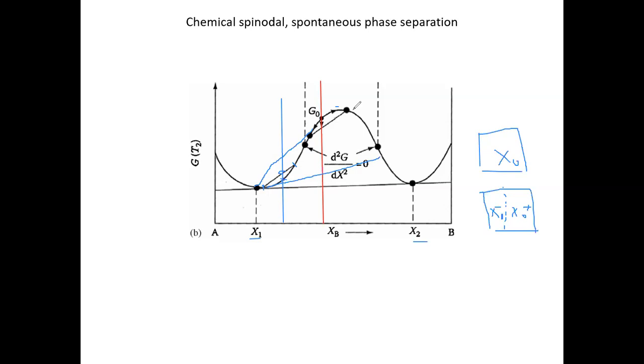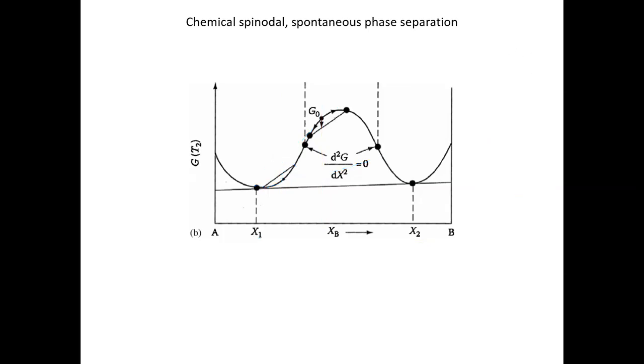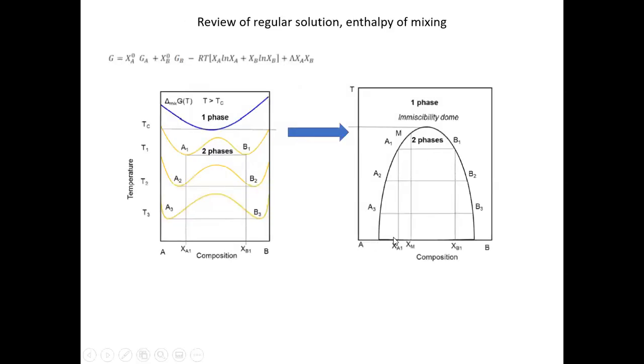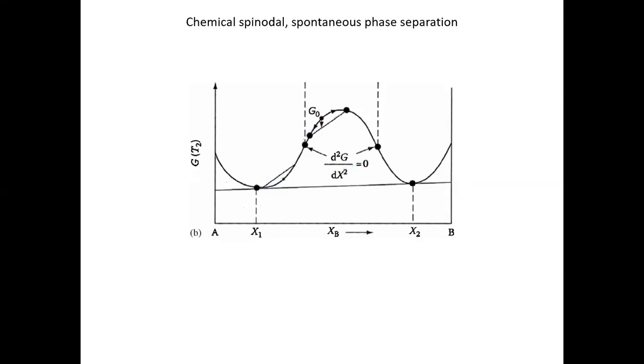So basically, from this very simple analysis, we see that although we can construct that dome, which I showed in the previous slide, something like this. Oops, why is it not working? Like this, right? And we know that any composition within this dome favors the two-phase coexistence as the more thermally equilibrium state, as the one with overall lower free energy. However, kinetically, if you look at the possibility of achieving that process, we see that not all the compositions within the dome are going to have an equal capability to really achieve that particular state of two-phase coexistence, right? We have good compositions, we have bad compositions.